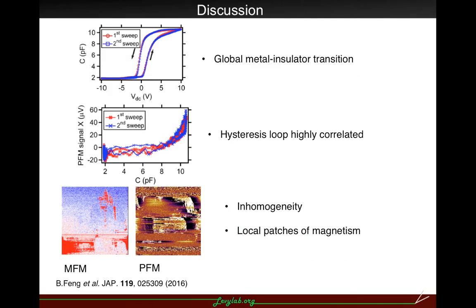So here comes the question: why would the MFM and the PFM have similar behavior? We studied the capacitance as a function of the DC voltage. We saw there is a huge enhancement of the capacitance near the metal-insulator transition point. This is due to the charge accumulation. And we also performed the PFM at a fixed sample location under different DC voltage. The parametric plotting of PFM signal versus capacitance shows the hysteresis loop is highly correlated.